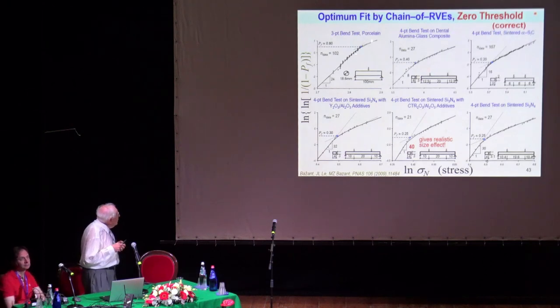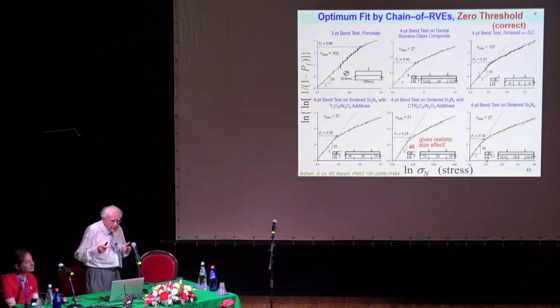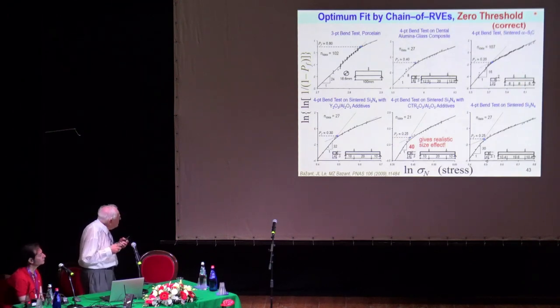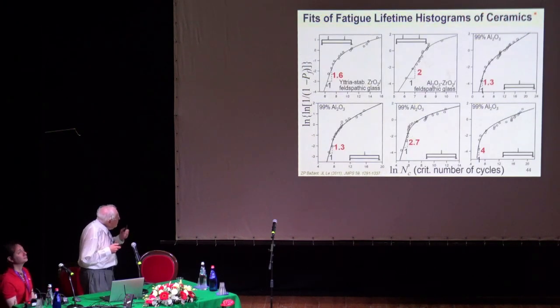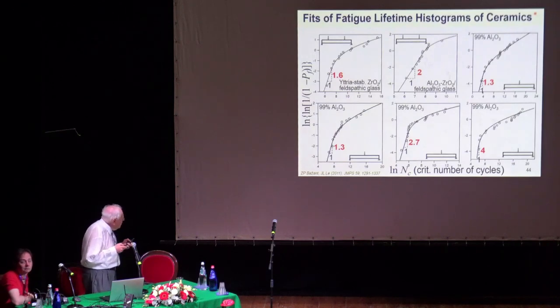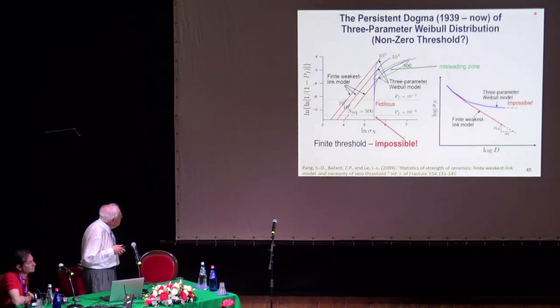So these are various ceramics behaving in a quasi-brittle way: porcelain, dental ceramics, silicon carbide, aluminum oxide, and so forth. It fits perfectly, these histograms. And in this field, they still believe this is a three-parameter Weibull distribution. That's not correct. It is actually the effect of the finite number of RVEs in their samples. It can be translated, and has been, into fatigue or static lifetime, both. Same behavior for static lifetime. Again, this is a review, so I will not go into detail, just want to point out what kind of implications occur.